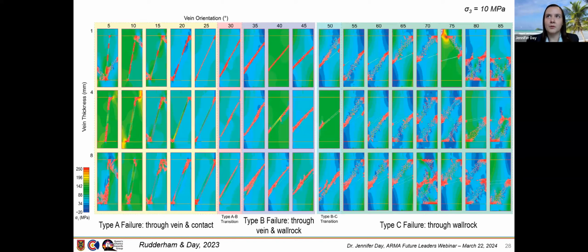So here's an example. Here's all of the 10 MPa confining stress rock types organized by vein orientation and vein thickness. And these are RS2 models, again, finite element. You can see as you go from the left side, where you've got a low angle, near a subvertical vein, it starts as type A failure, through the vein and the contact. And then as you increase that angle of orientation toward horizontal, you get more failure through the vein and wall rock, and then through the wall rock alone, and the vein is less and less involved.